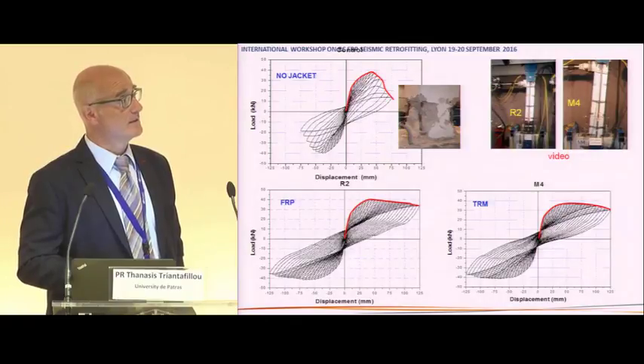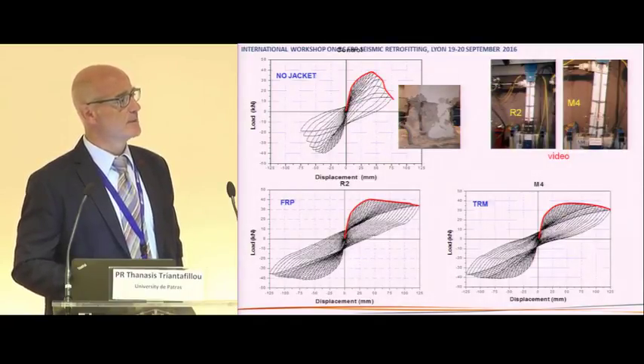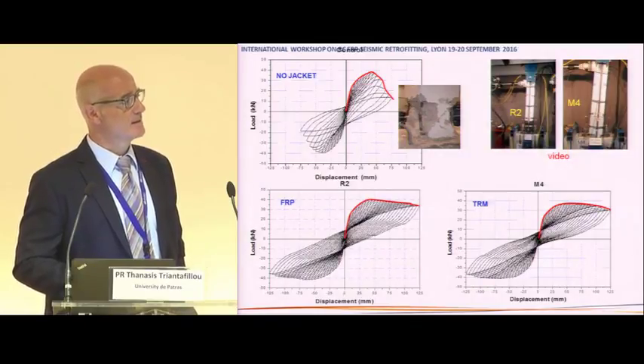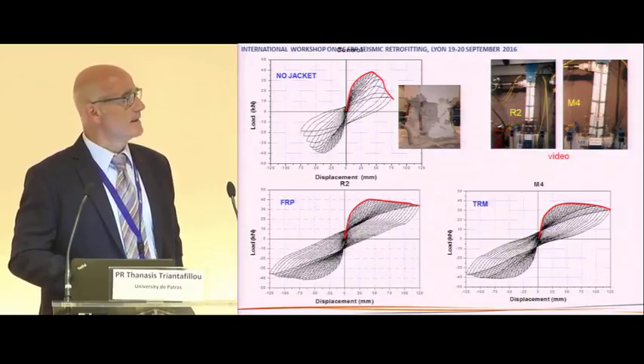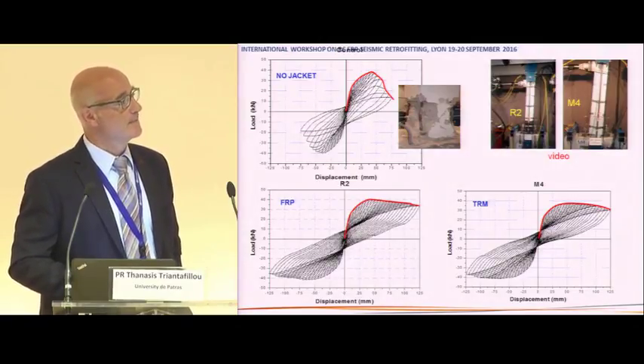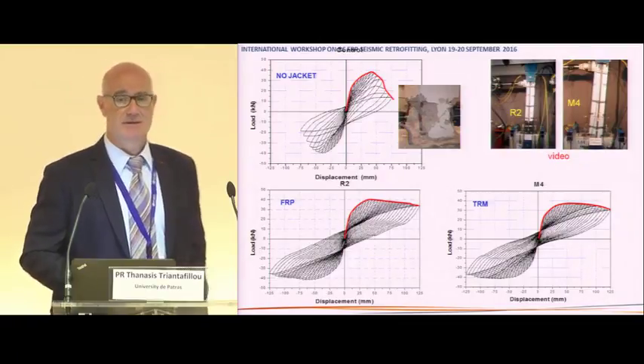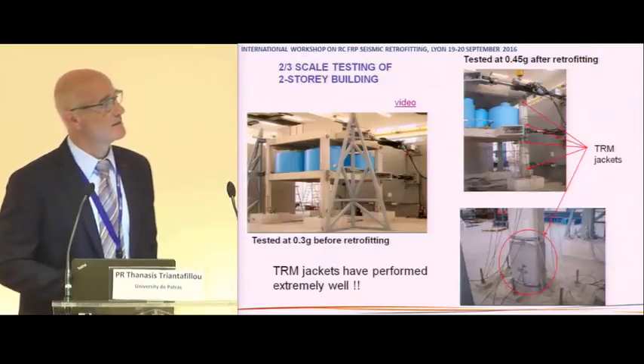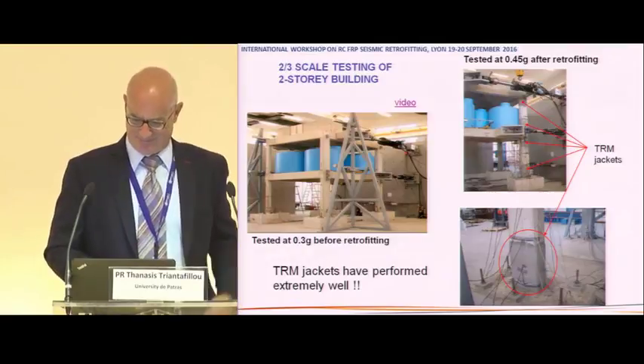versus what we get in the case of a control specimen without any jacketing, you see practically the same results. There is a lot of ductility, there is very little strength degradation, plenty of ductility, no stiffness increase with both the FRP and the TRM system. So they give us pretty much the same response.